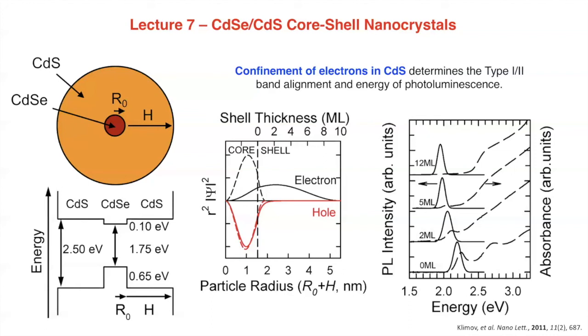And way down there in the baseline, you might see some transitions that are associated with the cadmium selenide part of the spectrum. But most of it is a cadmium sulfide absorption. And so you end up with this large apparent Stokes shift between this photoluminescence peak and the absorption onset. But actually, the Stokes shift that you need to be thinking about is the one between this cadmium selenide absorbance, or this one, and that photoluminescence. These are still on top of each other. You just don't see a whole lot down here because there's very little cadmium selenide in this final structure.